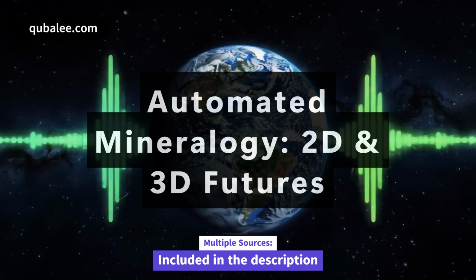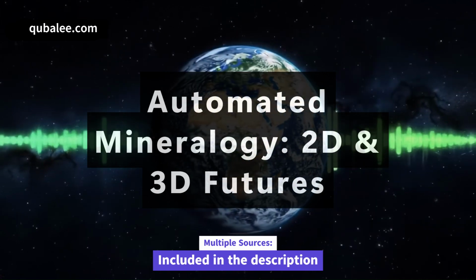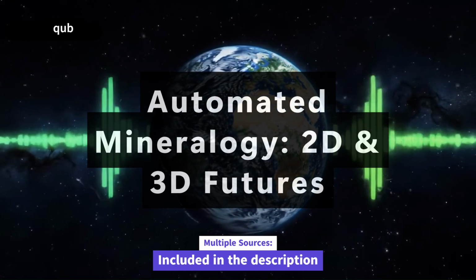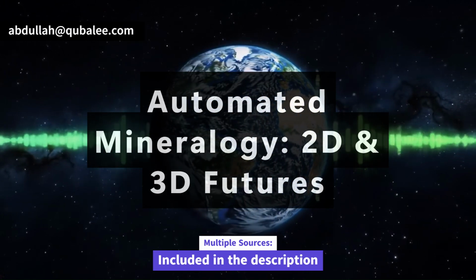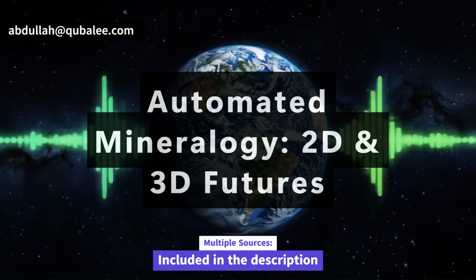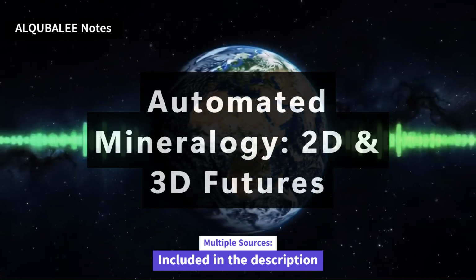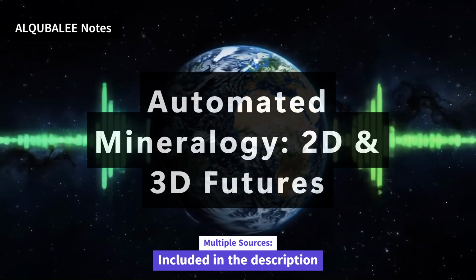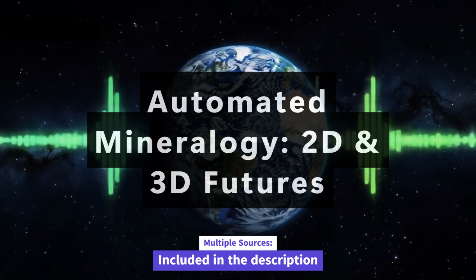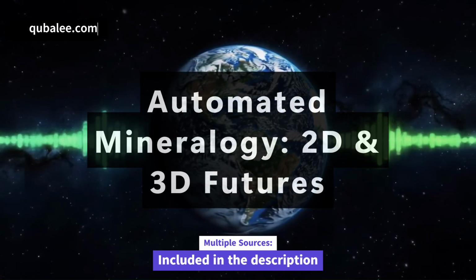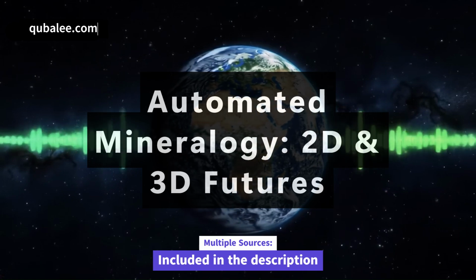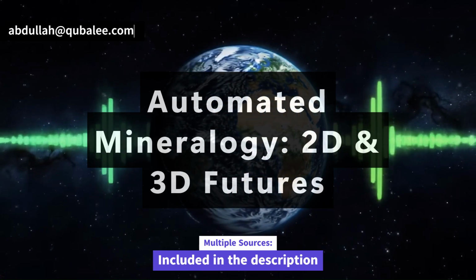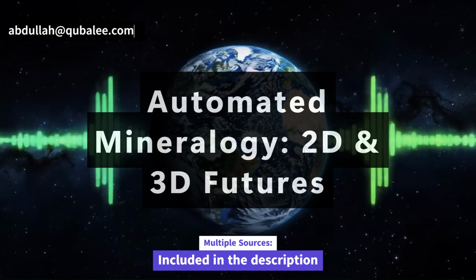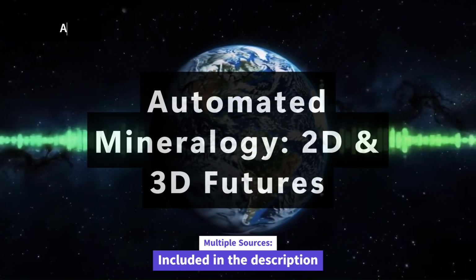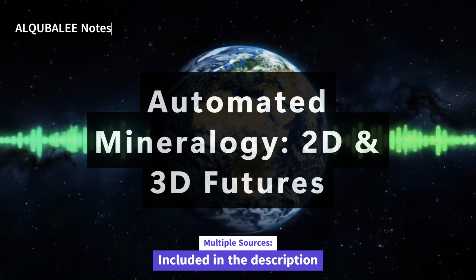But the tech has evolved quite a bit to handle tricky situations that used to be real problems for older systems. Tricky situations? Like what? Well, the sources talk a lot about the mixed spectrum problem. Yeah. At the boundary between 2 different mineral grains. Right. The beam might hit both at once. Exactly. The interaction volume of the beam is finite, so it can span across 2 or even more mineral phases. You get a mixed signal, a spectrum that's a blend. So what happens then? Does it just get confused? Not anymore, really.